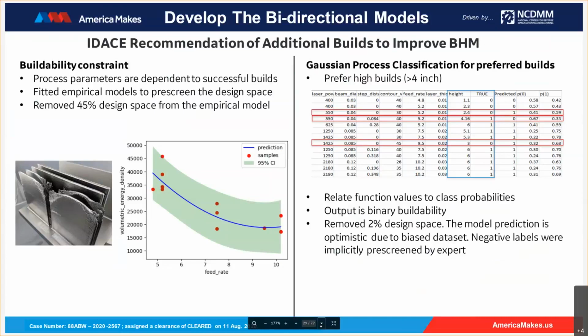And the second classification model is based on the Gaussian process classifier for preferred features. During the build, we would like the wall or some features, for example, for the thin wall, we would like the wall to be tall enough, like larger than 4 inch. So we are building a classification model to identify the process parameters which are more likely to give high walls. In this case, we came up with a binary classifier that tells you whether it's preferred or not preferred. Using this buildability constraint and a Gaussian process classification model, we successfully removed about 50% of the design space, which is less likely to be buildable, and then performed the additive build only in the remaining preferred domain. So next slide, Neil, please.